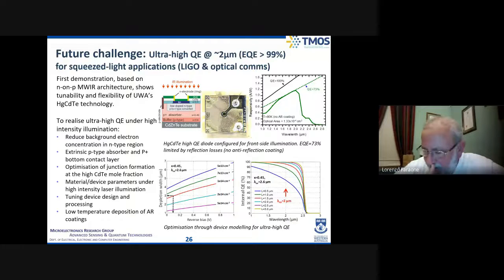It also means that 2 microns has been looked at as the wavelength of operation for the next generation gravity wave detectors in their interferometers, because they want to maximize their signal from the laser used. The other advantage at 2 microns is that there are high power lasers available, holmium doped fiber lasers. So this is an interesting challenge for the infrared detector community, because achieving quantum efficiencies greater than 99% is going to be a real challenge.